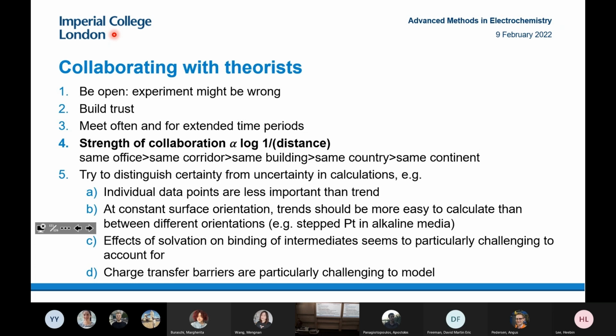So usually, if all you're changing is composition, keeping the same surface orientation, trends should be easier to calculate than between different surface orientations or between very different classes of catalysts. Let's say if you want to compare enzymes and metals. I think the effect of solvation on binding intermediates is very difficult to account for, and also charge transfer barriers are particularly challenging to model. This is something that Clotilde will talk about more next week.